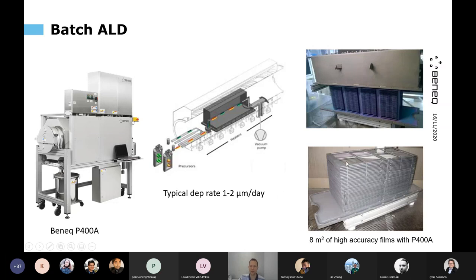But it can be done on a very large batch. So in this example, really the largest that this tool can do is about 8 square meters of coated area that we are coating simultaneously. So that's how we compensate the low deposition rate by bigger batch.